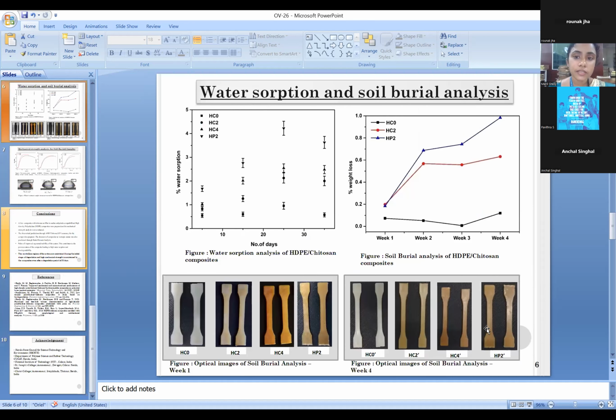The water sorption as well as the soil burial analysis of the prepared systems were also done. It was observed that after 30 days of studies, the composites having high chitosan content have shown high water sorption properties. Also, the soil burial analysis showed that with the increase in the concentration of chitosan, the composites have undergone high degradation.